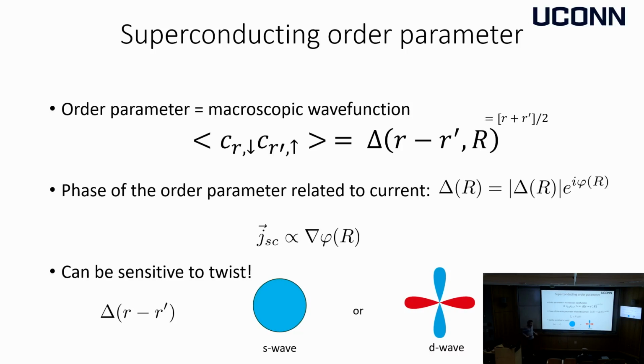And in most superconductors, the ones described by BCS theory, those pairs are isotropic, a little bit like the ground state of the hydrogen atom, S wave. But they can also be pretty anisotropic, and for example, the wave function of such two electrons can be sign changing. That's what I'm going to focus on in this talk, because precisely the properties of such superconductors are greatly affected by twisting, which is kind of already obvious from this picture. This kind of order parameter is not invariant under twist.